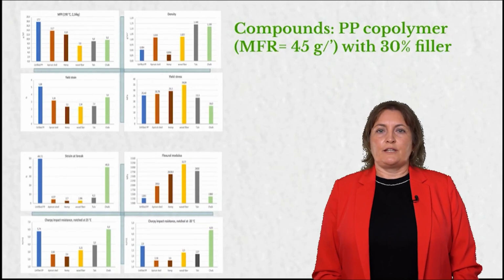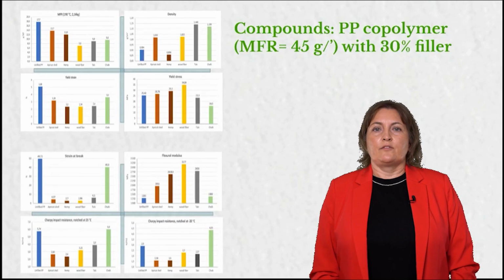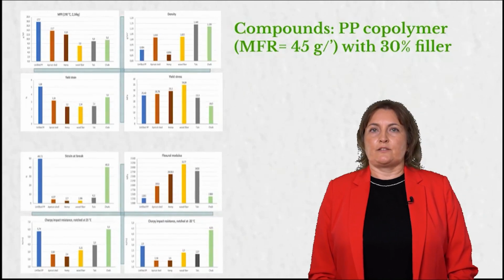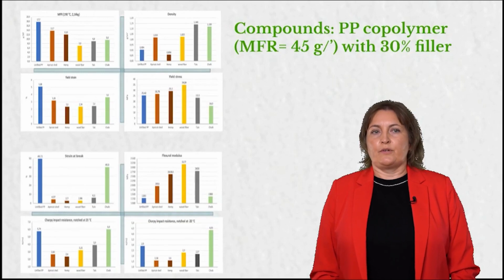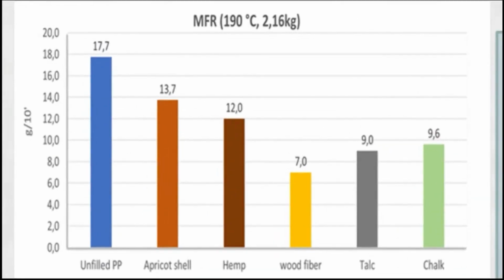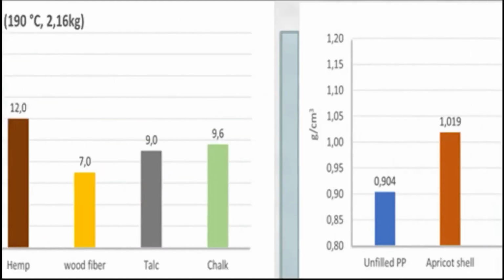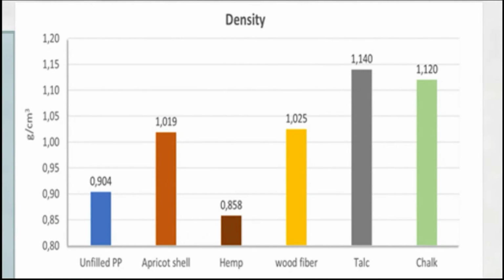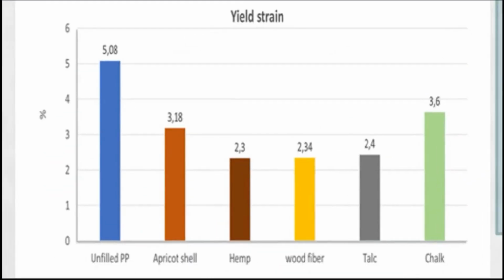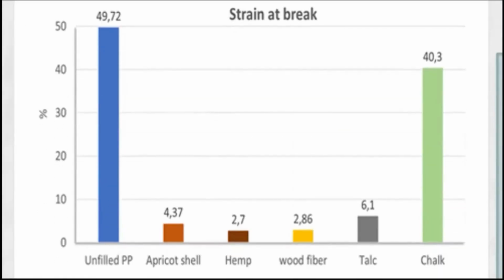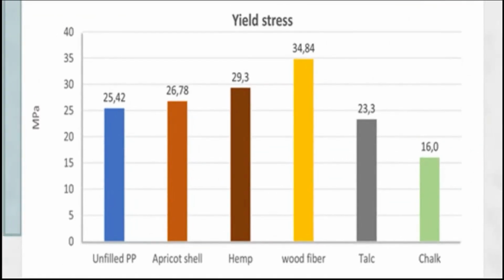In comparison to the base polymer, which is colored blue in each diagram, we can see the change in physical properties in the case of ground apricot shell, hemp, and wood fiber. Composite results filled with talc and chalk are also presented. The MFI value of the compounds containing natural organic and mineral fillers was almost the same and decreased by a similar value compared to the base polymer. The density of the biocomposites was around 1, which is much lower compared to PP filled with 30% talc and chalk. Yield strain and strain at break of the biocomposites is between that of the chalk and talc-filled compounds. Yield stresses are better than base polymer and other compounds.